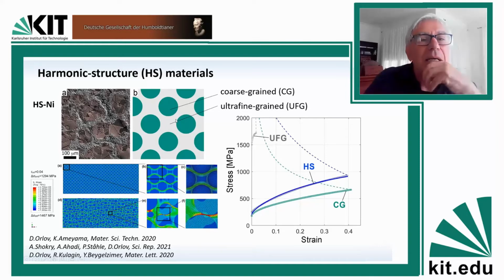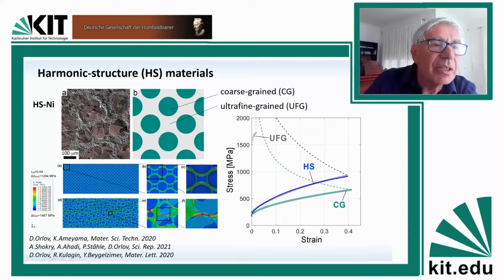They take metallic powders, in this particular case nickel. They do ball milling of this nickel so that the surface of the particles becomes hard and small grained, and the core remains soft. Then they consolidate this material by spark plasma sintering, and they get a material with a soft interior and hard shell around that interior.